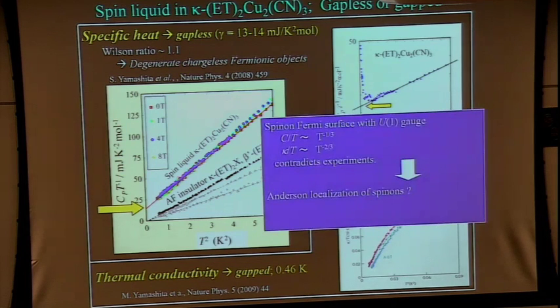But anyway, this contradiction. From the theoretical point of view, the experimental data, the finite gamma, is very clear and has a clear consequence that some independent fermionic stuff is there. But from the theoretical point of view, for the U(1) spin liquid, the theoretical prediction is that C over T should be proportional to a curious power law, and kappa over T is also a curious power law. So even though the data suggestively indicate fermionic stuff, it's still inconsistent with this U(1) gauge spin liquid. So some other spin liquid may be possible.